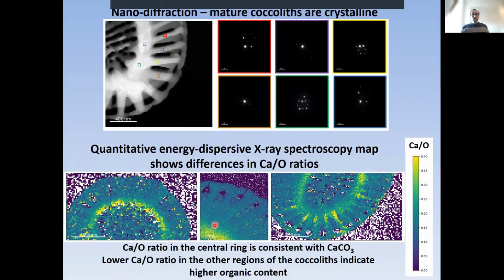As we go outwards, to the distal proximal element and away from the central ring, we see that the calcium to oxygen ratio decreases, which means that if you have more oxygen than calcium, very possibly we're talking about higher organic content in here compared to the central area. So that could explain the discrepancy that we see in electron density and the differences between the two areas. And it means that the composition of the coccolith, first of all, is not homogeneous throughout the calcium carbonate crystal. So I have regions here that contain a higher calcium to oxygen ratio, you can say higher mineral content, and areas that contain lower mineral content, a higher organic content. So that is a take-home message in here, and that matches well with the tomography at least.